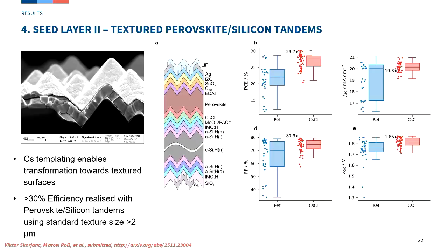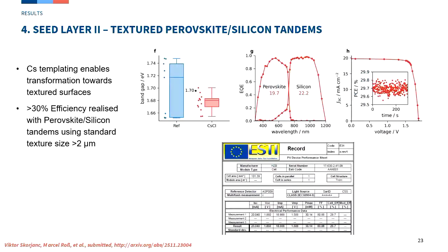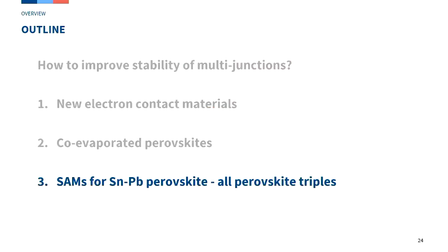And if you do everything right, with the seed layer the efficiency is higher and the spread is much reduced. We have an independently certified efficiency of close to 30%, which is a record for that technology using co-evaporation.